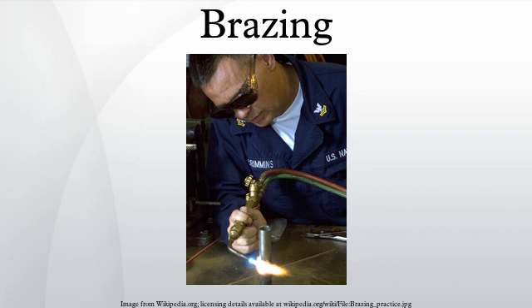Metals may diffuse from one base alloy to the other one, causing embrittlement or corrosion. An example is diffusion of aluminium from aluminium bronze to a ferrous alloy when joining these. A diffusion barrier, for example a copper layer, can be used. A sacrificial layer of a noble metal can be used on the base metal as an oxygen barrier, preventing formation of oxides and facilitating fluxless brazing. During brazing, the noble metal layer dissolves in the filler metal. Copper or nickel plating of stainless steels performs the same function.